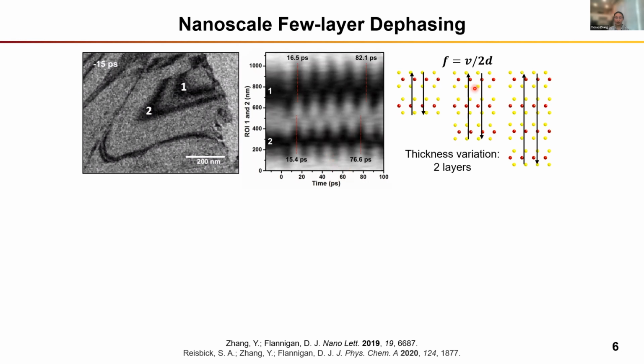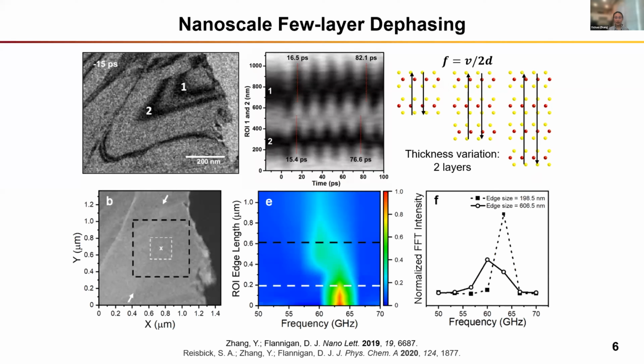So we have an equation here that describes the relationship between the velocity, the crystal thickness, and also the oscillation frequency. The slight variation in the thickness is then reflected in the mismatch of the oscillation frequency, which turns out to be 2 layers. The thickness difference is then verified by this very slight contrast in the ADF STEM image in this region, as pointed by the red or the white arrows here.